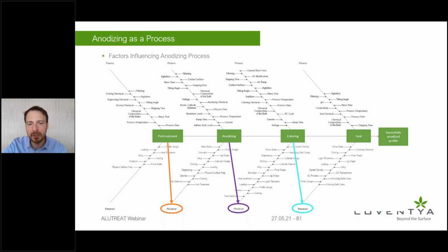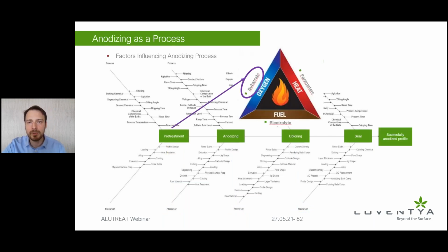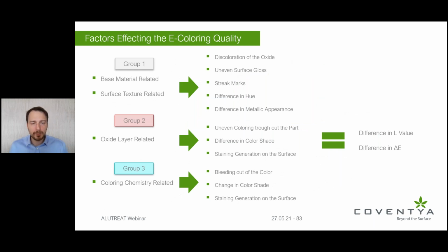But even that's not enough, because even if you're applying the perfect entry to the coloring phase, the parameters that you apply in the coloring cycle will determine the shade and the hue of what type of color you're going to get at the end of the day. So therefore, it is paramount to separate the problems that you're having on the line, or to look at the profile that you want to match by separating the problem sources. So you need to verify what type of underlying metal there is. Is it forged? Is it cast? Is it machined? And then the alloy, the heat treatment, so that you know what type of basis you have.